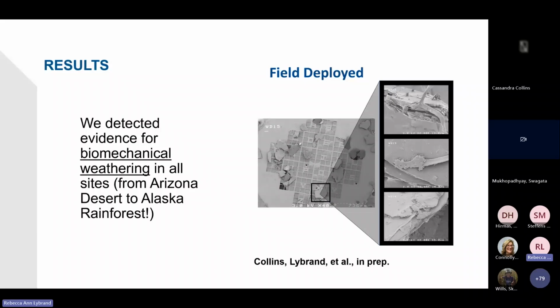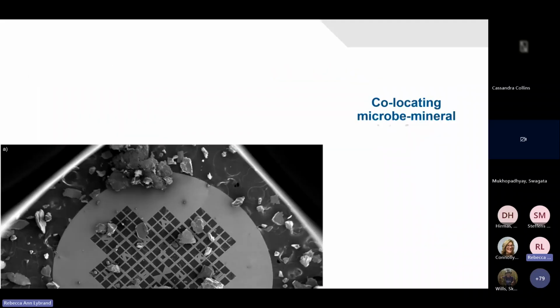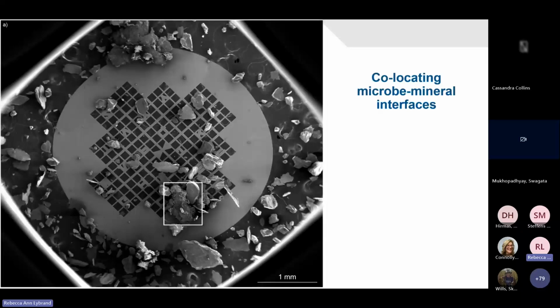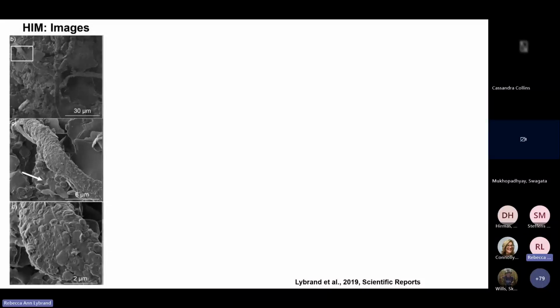The other important component that I wanted to include here for thinking about techniques and microscale analyses is that you don't necessarily have to use just one type of high resolution advanced capability. One of the techniques that we developed and demonstrated was how to co-locate microbe-mineral interfaces across different types of microscopy approaches. This approach involved identifying fungal grain interfaces using helium ion microscopy, and then identifying that same exact fungal grain interface where we could collect chemical information using scanning electron microscopy. And so this was a win-win.